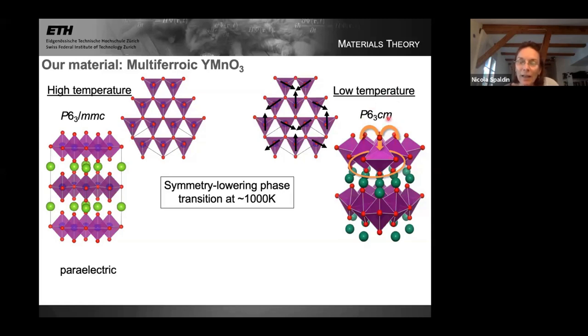A second structural distortion accompanies this one, and that's the shuffling of the yttrium ions, all relatively in the same direction, relative to the manganese oxygen layers. Because the yttrium ions are all cations, all three pluses, this introduces a polarization and makes the low temperature state ferroelectric. Okay. So that's the symmetry lowering phase transition from a paraelectric to a ferroelectric structure, at very high temperature. It's a very robust low temperature structure.